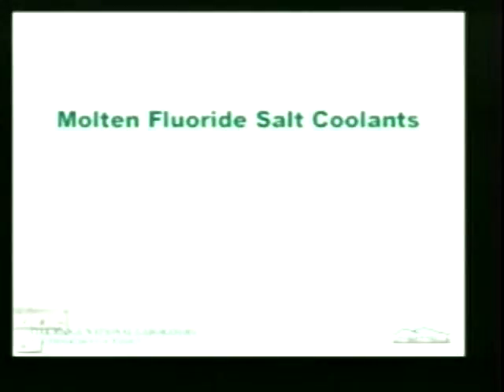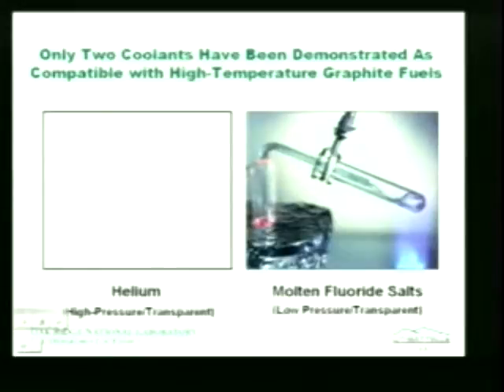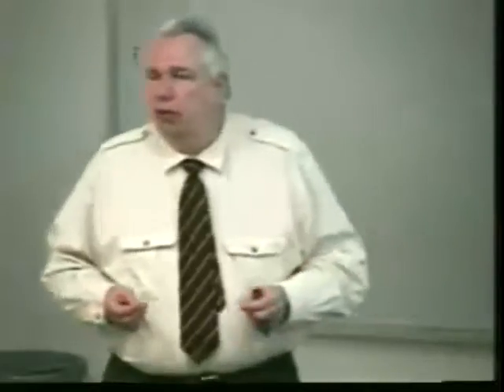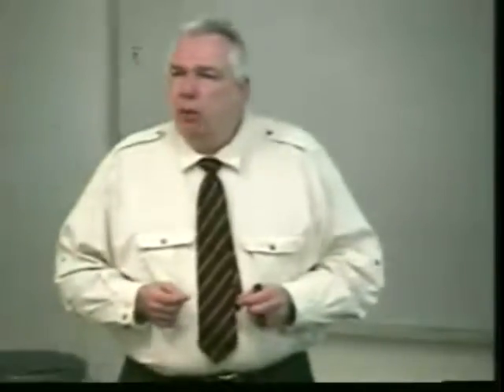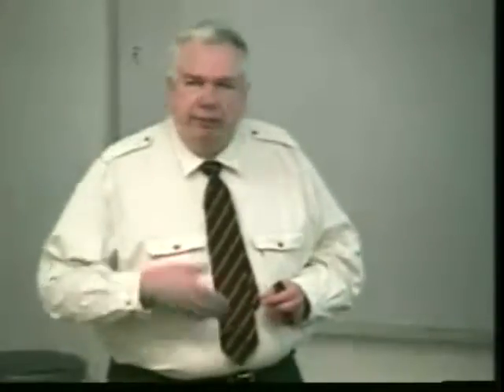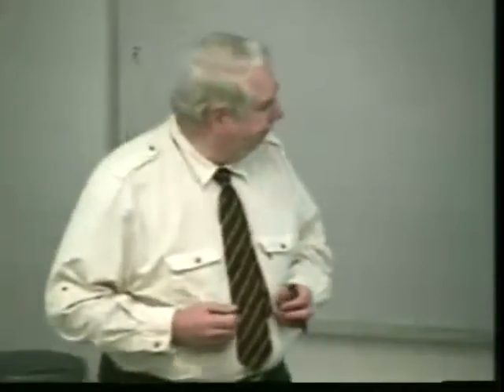Molten fluoride salt is the coolant we've chosen. The basis for this is quite simple. Only two coolants have been demonstrated compatible with high-temperature graphite. The first is helium, high pressure, transparent. And the second option is molten fluoride salts. Note that the salt is transparent. You can see right through it. These salts typically have melting points of 400, 450 C, boiling points of about 1,400 degrees Celsius. Very high boiling point fluids.